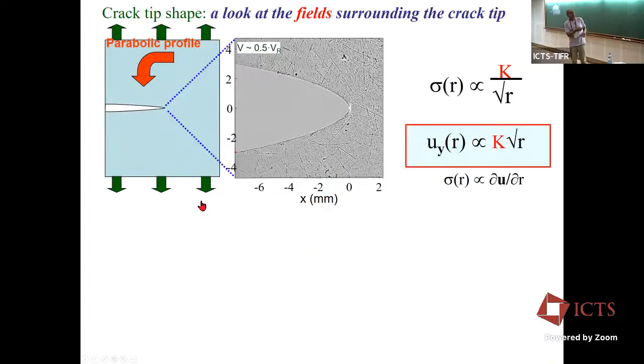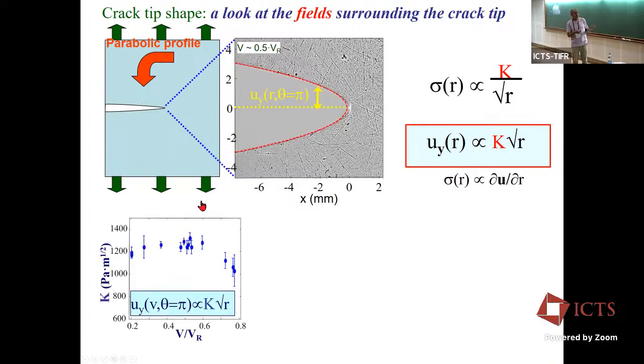So here's a cartoon of the parabolic profile, with the same K that's the singularity. The displacement fields at the boundary are parabolic because the derivative of this gives us the strain or stress field. So the displacement in the y direction goes like the square root of r. So we have parabolas on their side. That's what things should look like. Okay, this is a cartoon. This is a snapshot of a crack moving at about half of the Rayleigh wave speed where we suppressed all of the instabilities, and this is a fit to this theory. And it seems to work actually pretty well.